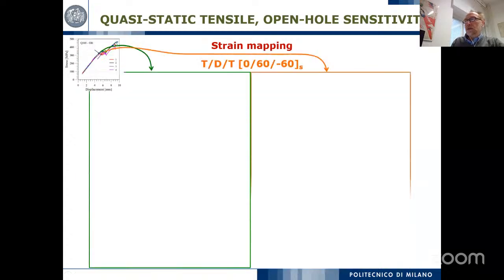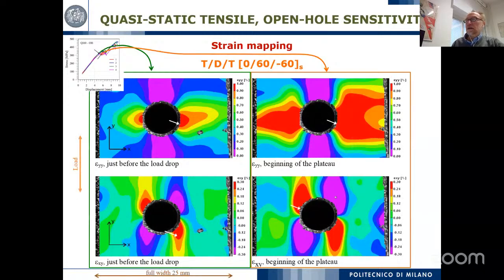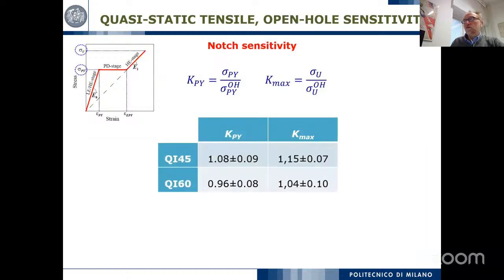And this is quite similar for the other quasi-isotropic laminate, showing the distribution of the strain during loading, mainly at the beginning of the plateau. But what is important is the notch sensitivity, because this pseudo-ductility, or this increase of strain that we can get at this load level, gives us a good understanding of the notch sensitivity that I show here, both in terms of notch sensitivity at the stress at the plateau level, and also at the final strength.